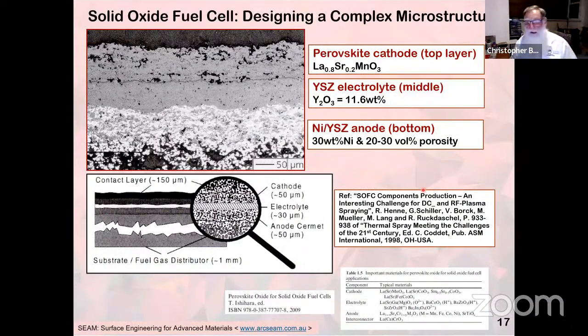Here's another relatively old example. This is not new, but it's the spin on how to use these features. So 20 years ago, we have the solid oxide fuel cells, again in Germany, from Professor Henne and others. I should also mention Professor Heberlein, who did quite a lot of work in this area. And here we have quite a complex structure of a perovskite cathode, where porosity was desirable, an yttria-stabilized zirconia electrolyte where density was desirable, and a functionally graded nickel yttria-stabilized anode where the porosity and density varied in the thickness.